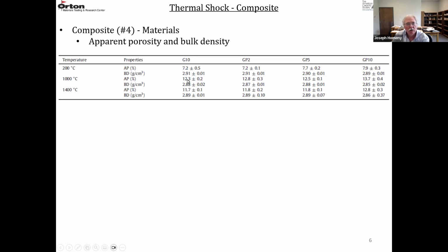Then at 1000, the porosity goes up to around 12% for all of them. This one's 13. And that's because the weight loss during coking, where you pyrolyze the resin. And then the bulk density goes down a little bit because of the weight loss. And at the highest temperature for coking, 1400 degrees C, the bulk densities maybe go up slightly. The porosities maybe go down slightly because of some sintering processes taking place and densifying the material.